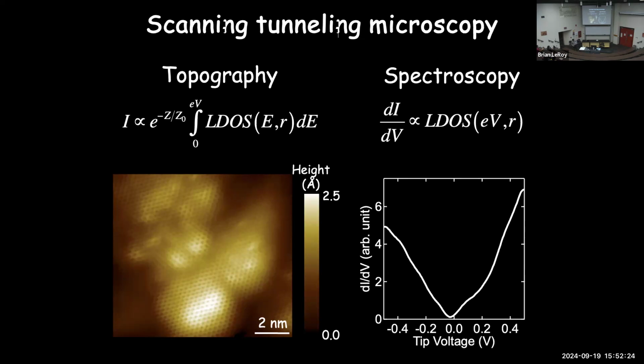I'm going to show you a lot of these types of images here. So this is density of states as a function of energy. There are very few states here, and you can see it increases as we go either direction from here. This is the characteristic spectrum that you get for graphene. I showed you earlier, right? The energy versus momentum relation was this V-shaped cone. In the density of states, what that shows up as is these kind of linearly increasing bands on either side.